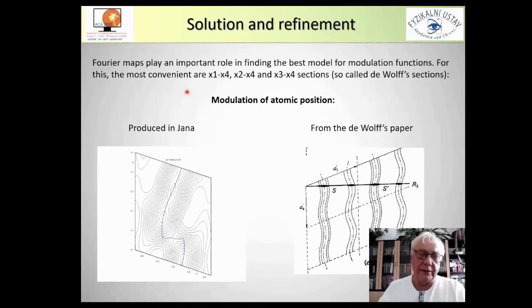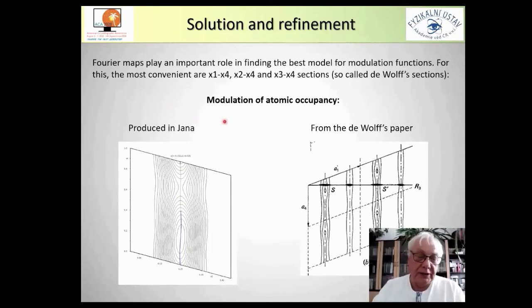What kind of function to use to describe the modulation of each parameter? For this, we very often use so-called t-plots. This is a section through four-dimensional space, taking just one atomic position and following the modulation curve along the extra coordinate. You can see that it is very closely related to the original paper from 1974. Here is another example of using a t-section. This demonstrates occupation modulation in a crystal, a map produced in Jana, and the same map produced in the original paper. From this you can see that these maps can help you to find the proper modulation of each atom in the structure.